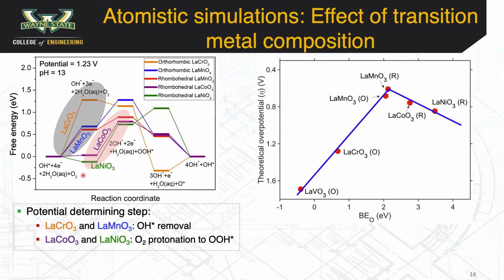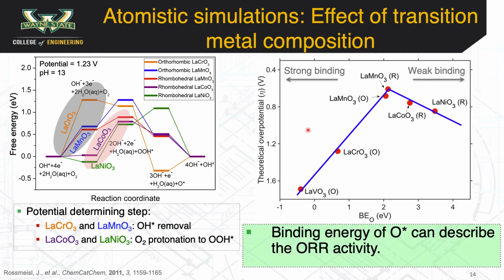One can then convert such free energy diagram type analysis into a volcano type analysis, where the binding energy of oxygenated intermediate O exhibits a volcano type relationship with the theoretical overpotential. Oxides on the left leg of this volcano are limited by strong binding, while oxides on the right leg are limited by weak binding. This is consistent with previous literature reports.